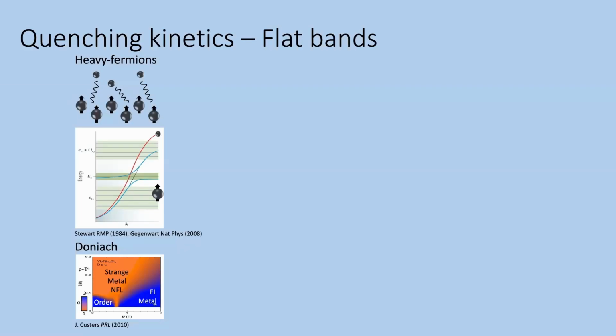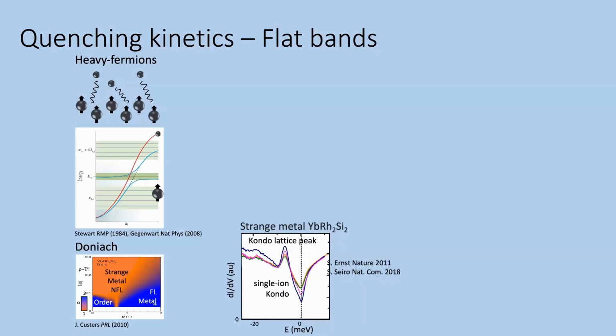And here I'm showing you an example of ytterbium rhodium silicon, one of the canonical materials that give rise to this kind of phenomenology. What is usually seen spectroscopically in scanning tunneling microscopy or planar junction spectroscopy is this kind of spectrum, a peak and a dip in the tunneling density of states, where the peak is associated with the flat band and the dip is associated with the Kondo hybridization gap that forms in the material. So this is the standard spectrum that signifies these heavy fermion systems.